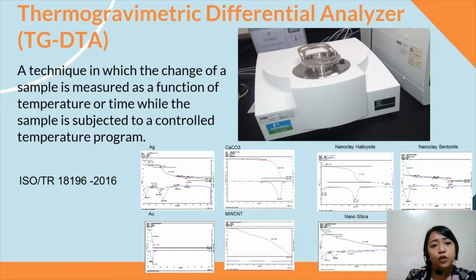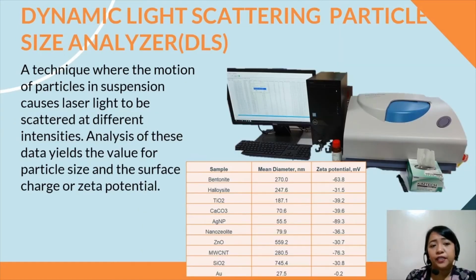Okay, and then we also have the thermogravimetric differential analyzer, or TGDTA. It's a technique in which the change of a sample is measured as a function of the temperature or time while the sample is subjected to a controlled temperature program. Dynamic light scattering particle size analyzer, or DLS, is a technique where the motion of particles in suspension causes laser light to be scattered at different intensities. Analysis of this data yields the value for particle size and the surface charge, or zeta potential, of your material.